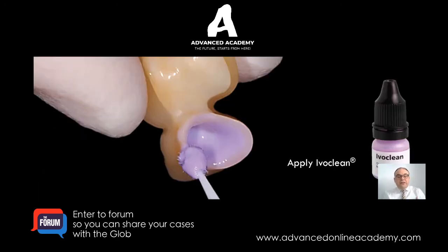If you have a zirconia crown, you're going to try it in the patient's mouth, and then when you take it out and you're ready to cement, this surface is contaminated. The very lipids and proteins from the saliva and blood, if you have bleeding around the gingiva, will contaminate the zirconia surface. Nothing will get that cleaned off.